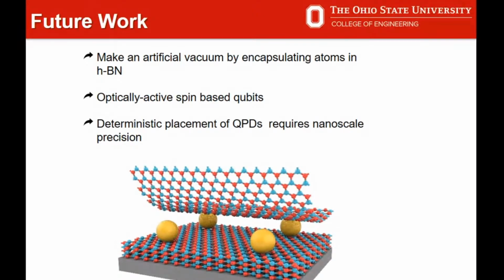So we are thinking about creating some artificial vacancies. People are growing materials and getting some defects, and based on the defects, they are claiming some kind of quantum emission by doing measurements like Hanbury Brown and Twiss interferometry or g2 measurements. But we are thinking about deterministic placement of QPDs, like quantum point defects. All this requires nanoscale precision. Initially you have to grow a material, then you have to adsorb some foreign atoms, and then you need to encapsulate those foreign atoms with another layer of hexagonal boron nitride. This is a very rigorous task. I don't know how I will do it, but we have come up with an idea that it's possible.